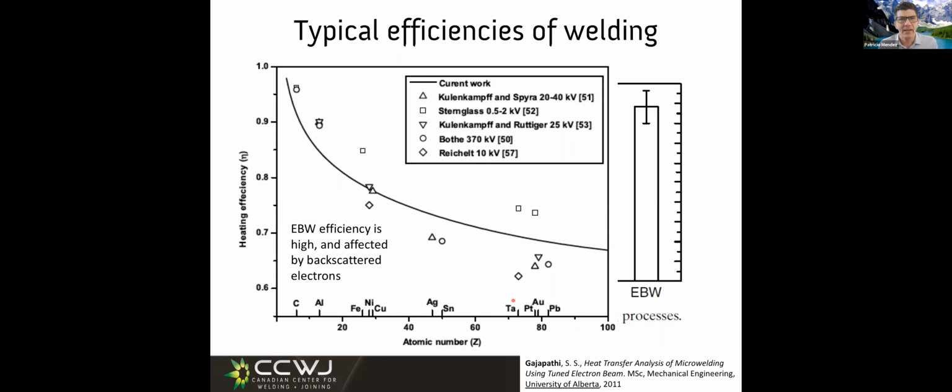But those electrons that are backscattering are taking energy away with them. And the same happens in electron beam welding. That's quite awesome. There are formulas for calculating the amount of backscattered electrons. If you have heavy elements, the electrons bounce off like a ping pong ball. And if the elements are lighter, the electrons can penetrate and stay there, with less backscattering. That's the reason we see the contrast we see in backscattered SEM, right?